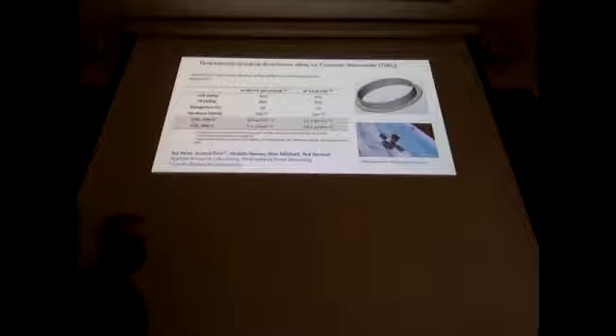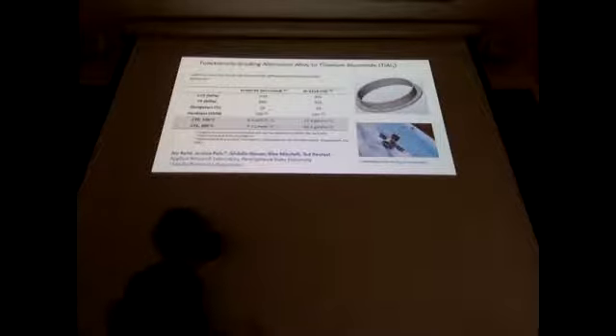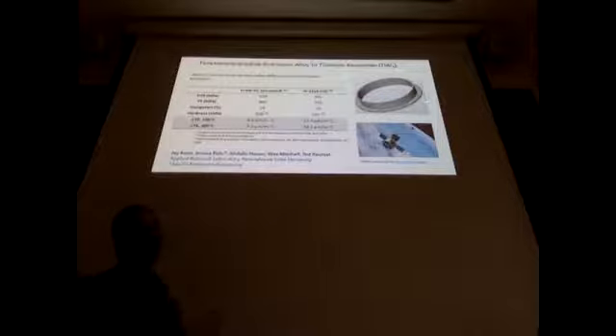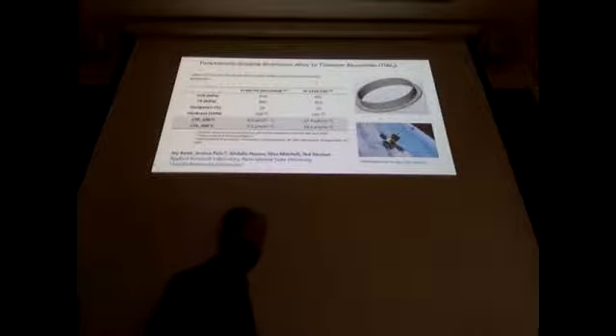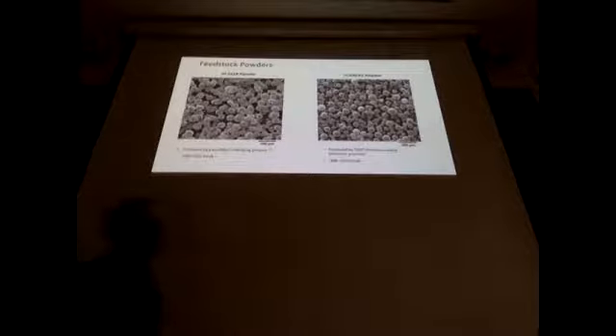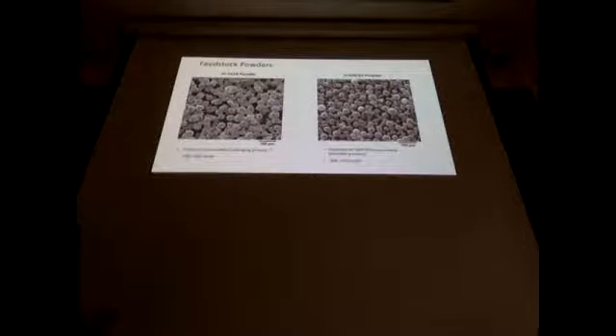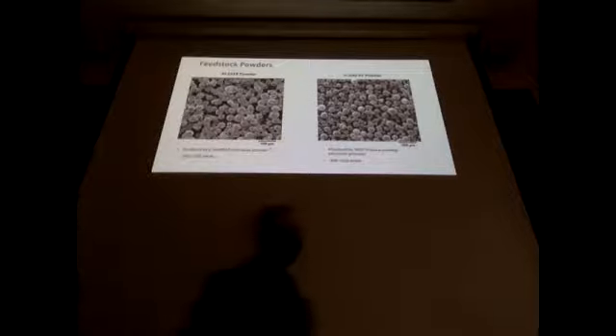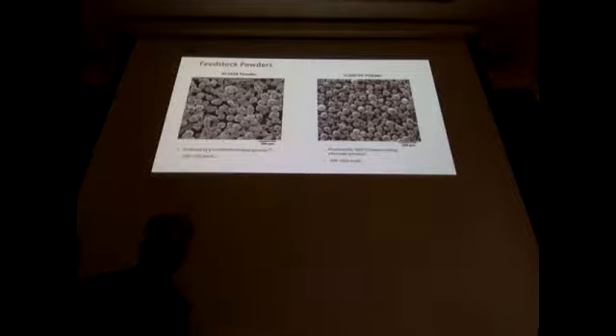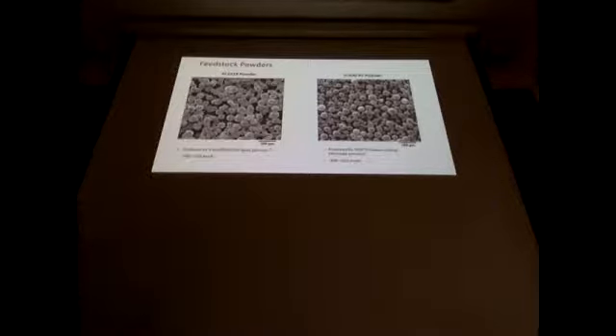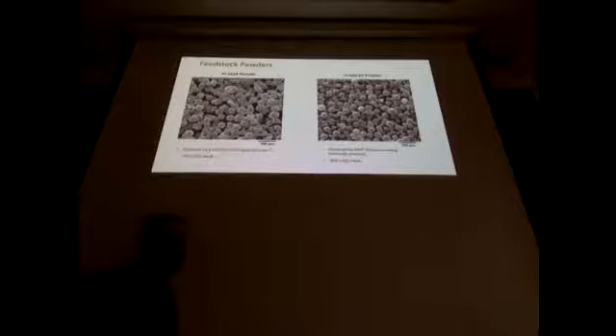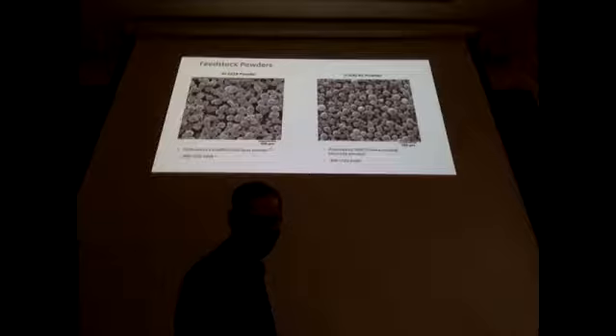So that was our initial thought: okay, great, we can make a coupling where we build one side as aluminum, and then slowly grade over to a titanium alloy. So we got 2 materials. We just used a Ti-64 PREP powder, a powder made by the PREP process, nice and spherical. And then we modified a cold spray apparatus at Penn State to make some 2219 powder, an aluminum alloy. This is an aluminum copper alloy that's used for welding. It's known to be a very good welding alloy, and it's also heat treatable, so we can get the high strengths that Sandia National Lab was requesting.